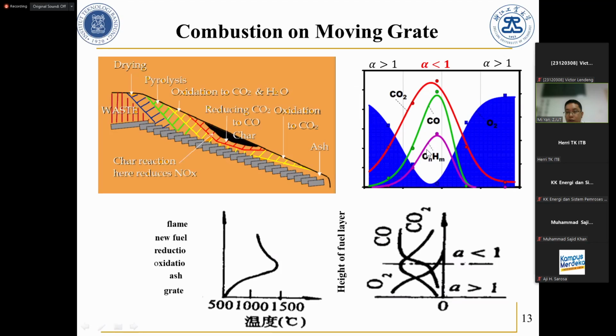So this is the composition of the flue gas. The CO2 is highest in the middle area. Alpha means the excess air ratio. So alpha larger than 1 means there is more air. Alpha smaller than 1 means the air or oxygen is not enough, meaning it has been consumed or converted by the combustion. And this is the vertical layer. At the surface is the flame, then the new fuel, reduction, oxidation, ash, and grate.